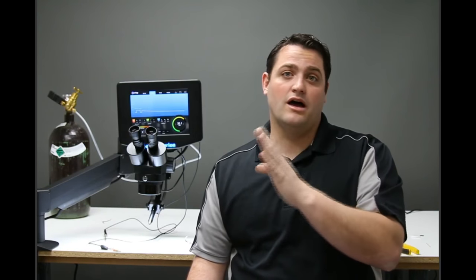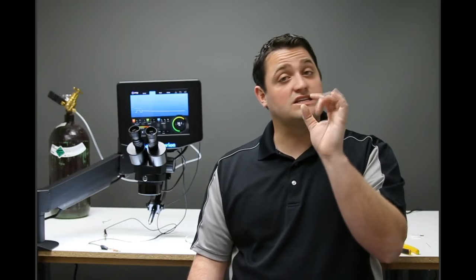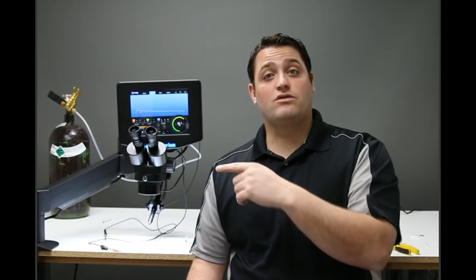That's kind of the power setting. With a laser we can adjust the spot size and the power individually. On the Orions, we don't have as much control over that. To get a smaller melt spot, we go down to smaller energies, and for a larger melt spot, we increase the size of that melt spot as we increase the energy. So they're tied together. The bigger the spot, the more energy we want. As we mentioned, we need to increase the energy. What we're saying is we need to put more heat and a bigger spot into it.